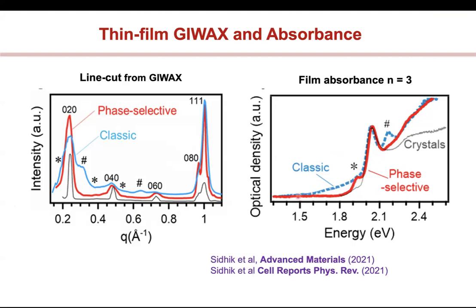Okay. So we found a way to get a 2D perovskite film that's very, very pure, in this case more than 90% pure. And we do have small impurities, which is shown by this little star. And you can get the same in X-ray diffraction. Typically, you get these peaks which are equally spaced. Look at the red curve here, and that is a signature of a phase pure 2D perovskite.